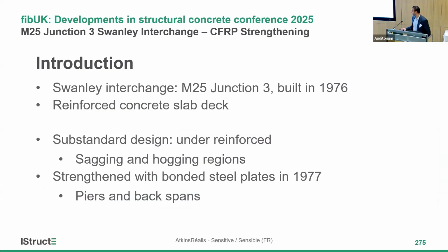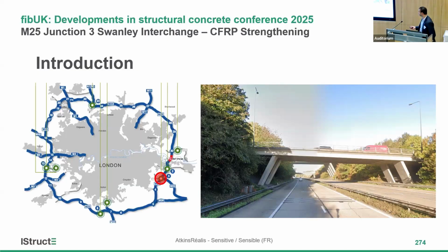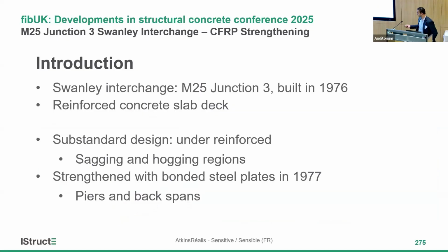The structure was built in 1976, and as soon as it was open, they noticed flexural cracks in the soffit on the back span and on the parapet locations on both the structures. So they realized, after doing investigations, that the structure is under-reinforced. So they carried out strengthening in 1977 using bonded steel plates at both locations, on top of the piers in the hogging regions and at the back span supporting the sagging locations.